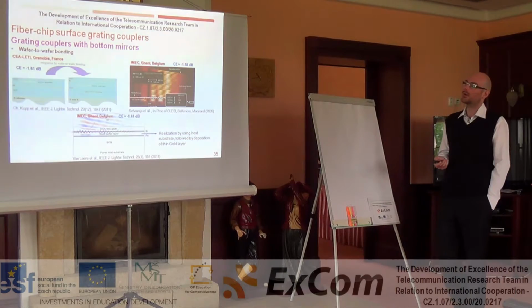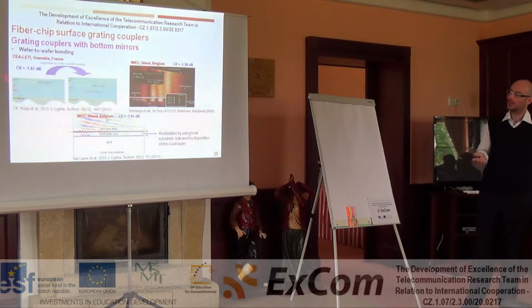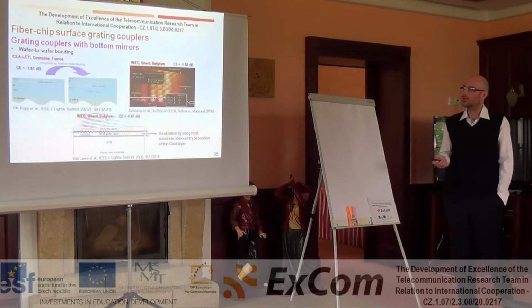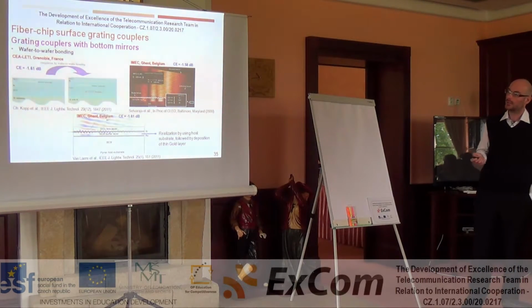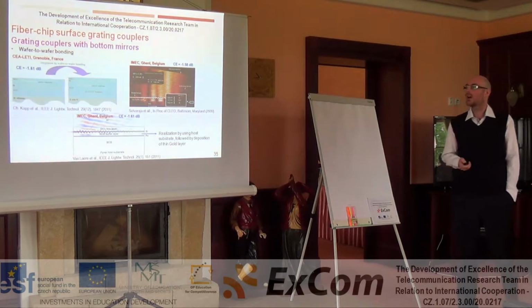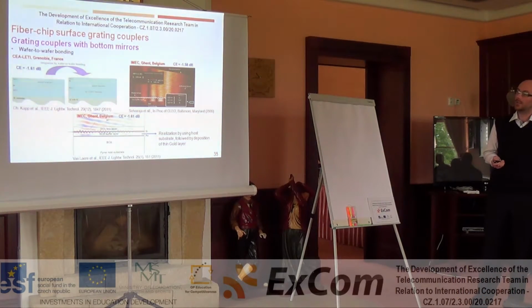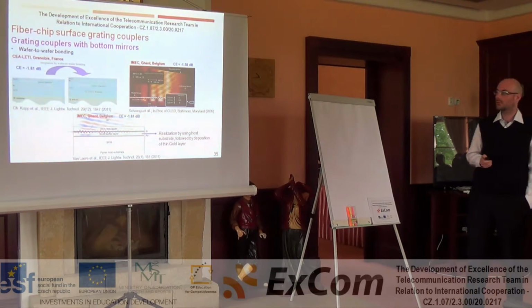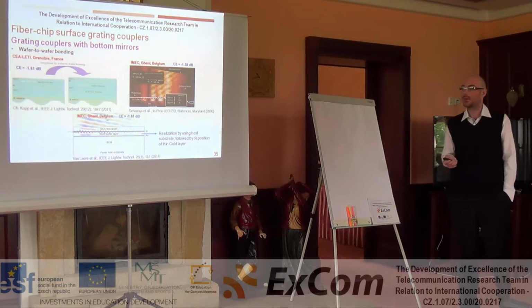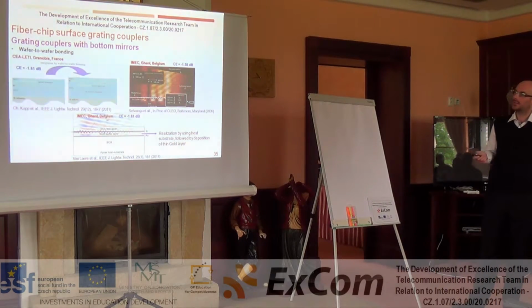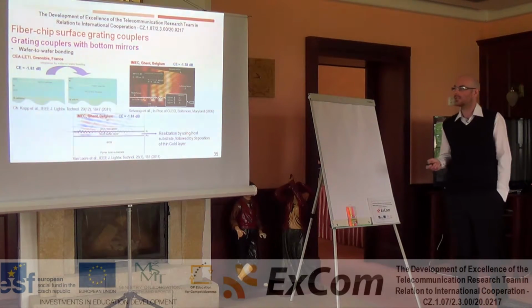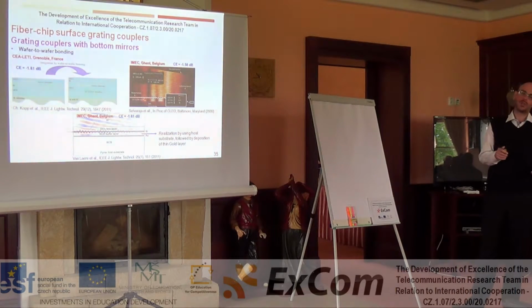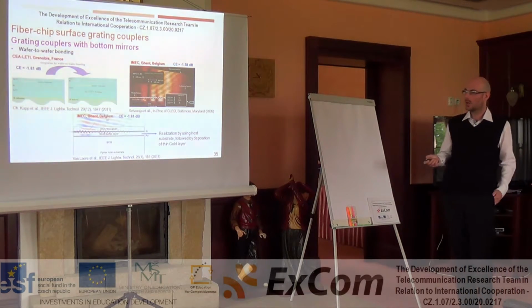Some of these approaches have been implemented, for instance, by CEA-Leti from France. By using wafer-to-wafer bonding, they achieved 1.6 dB coupling efficiency. In a similar way, the IMEC group from Belgium has demonstrated a grating coupler with distributed Bragg reflector, and they achieved -1.58 dB, and the same group has demonstrated the combination of both approaches.